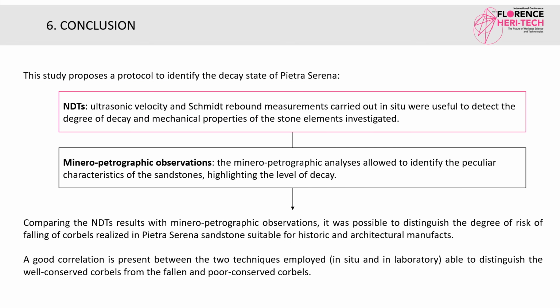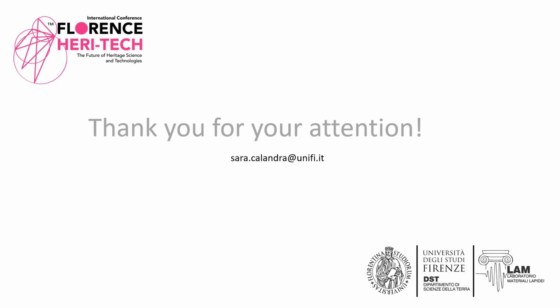In conclusion, this study proposes a protocol to identify the decay state of Pietra Serena using NDT techniques in order to implement a specific database able to distinguish the risk degree of falling of corbels, where it is not always possible to take sufficient samples. Comparing the NDT results with mineropetrographic observation, it was possible to identify the level of decay of 5 case studies belonging to Florentine historical palaces and to observe a good correlation between the two techniques employed in situ and in laboratory. Thank you for your kind attention.